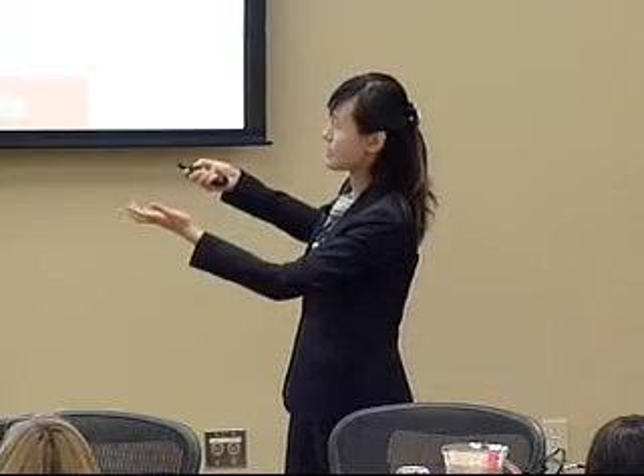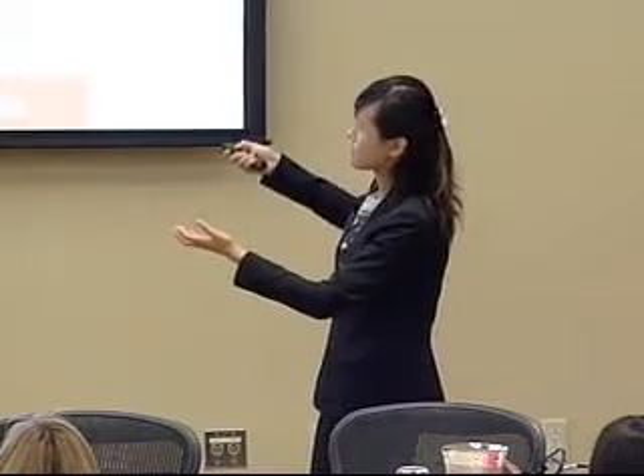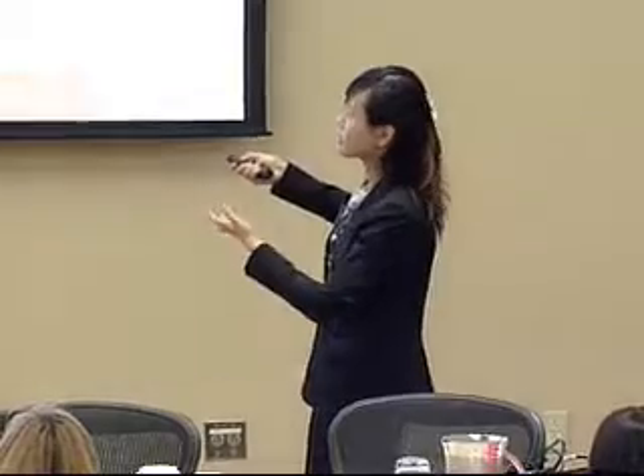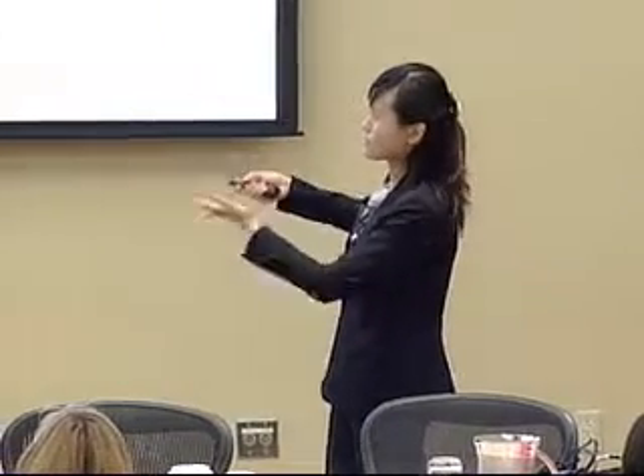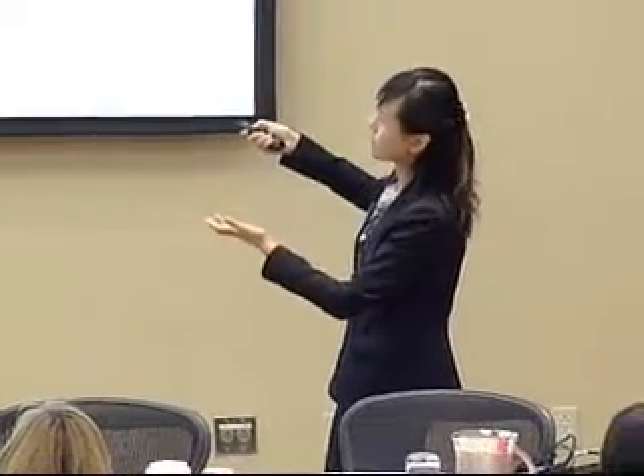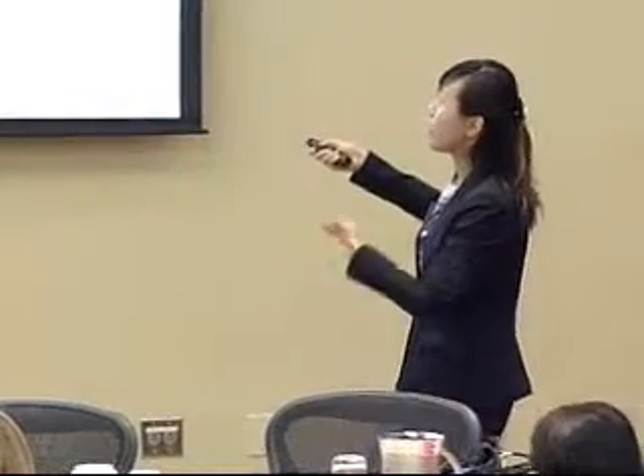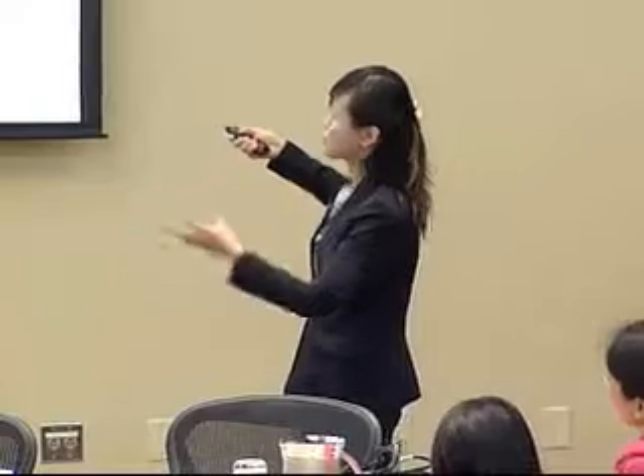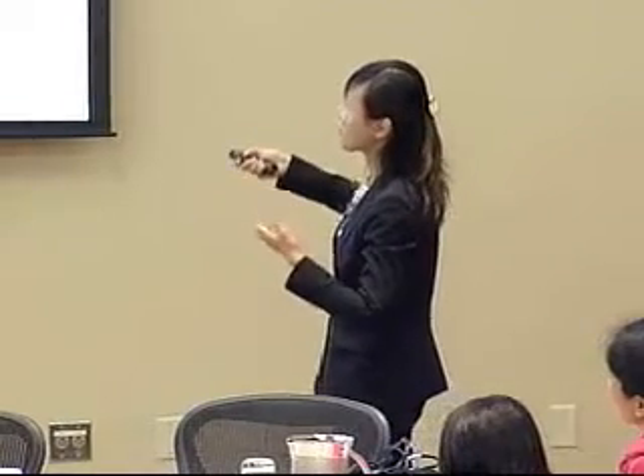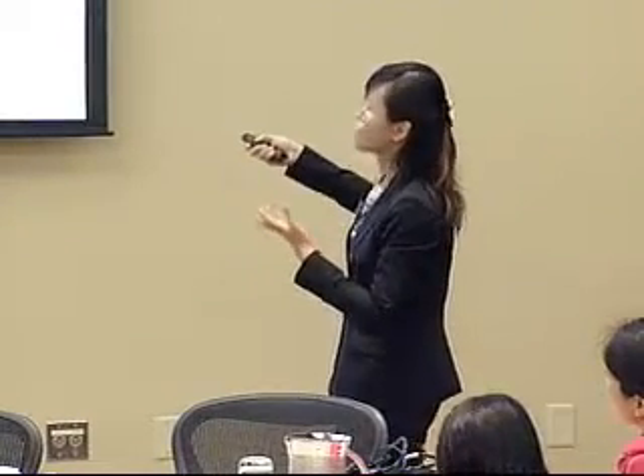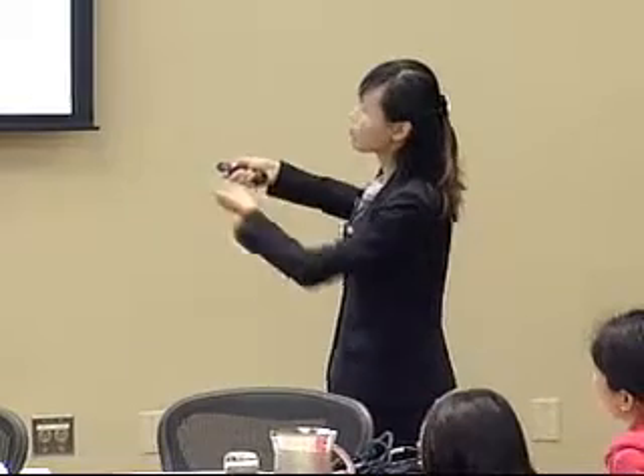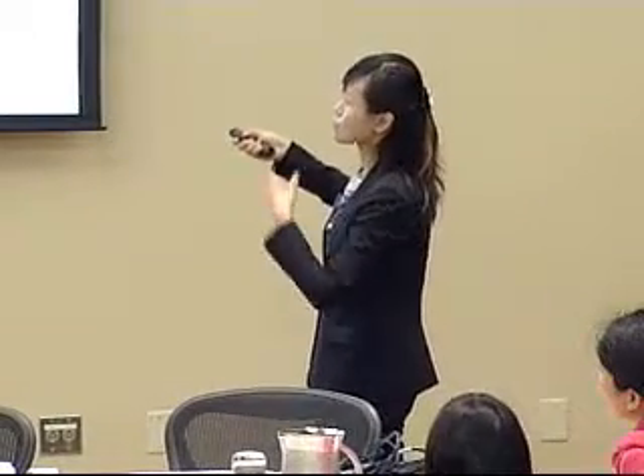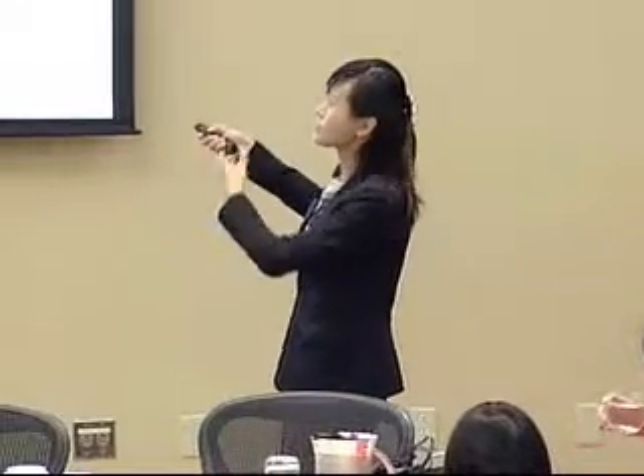This is the resistance change. And when they deviate from this theoretical prediction, that denotes the micro cracking. And we do see a lot of micro cracking at about 20% elongation. And when we have very good adhesion and very soft film, we see only a very gradual increase of resistance with the elongation. And that's purely due to geometric effect. There's no micro crack even after 60% elongation.